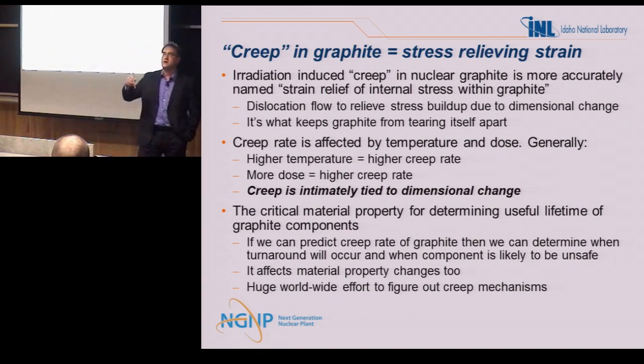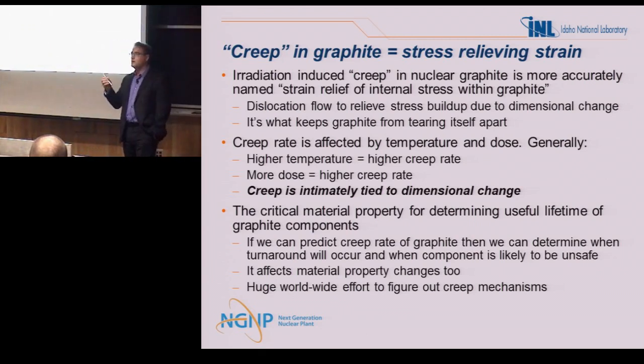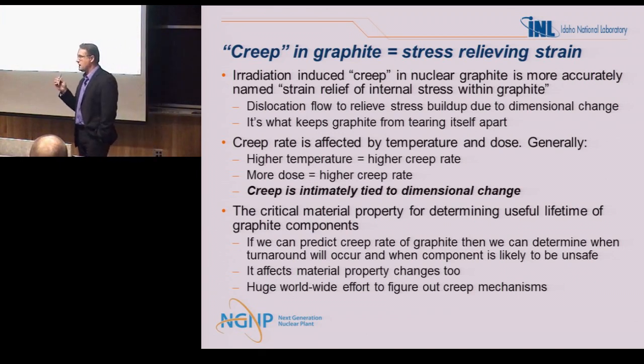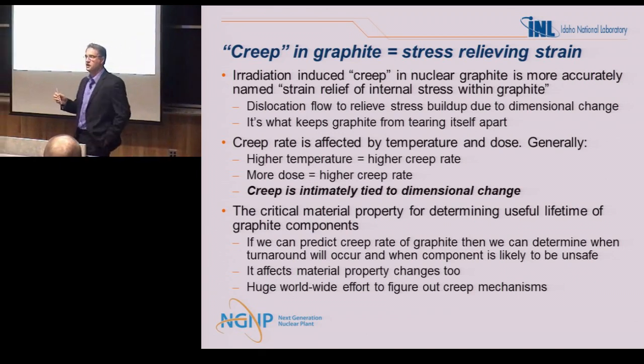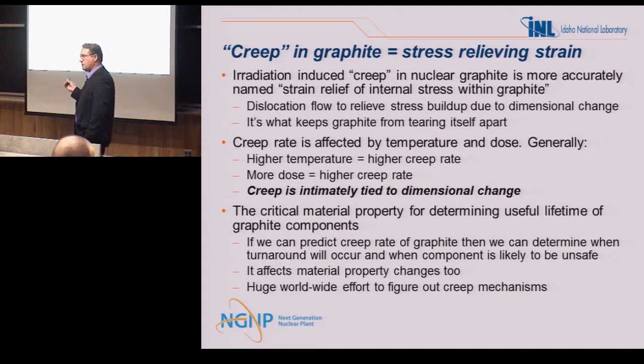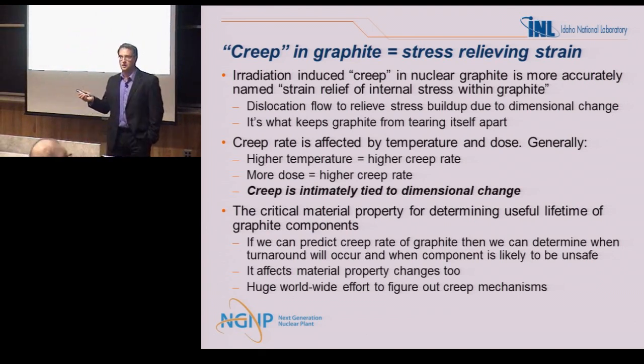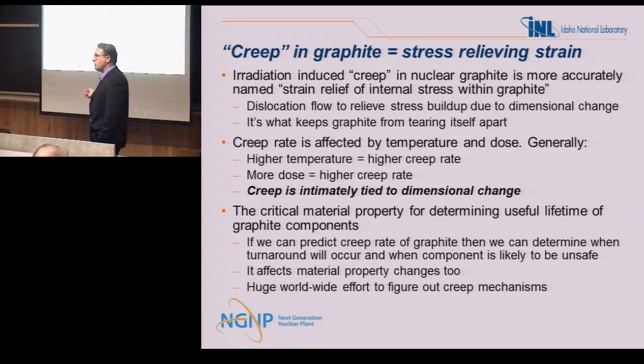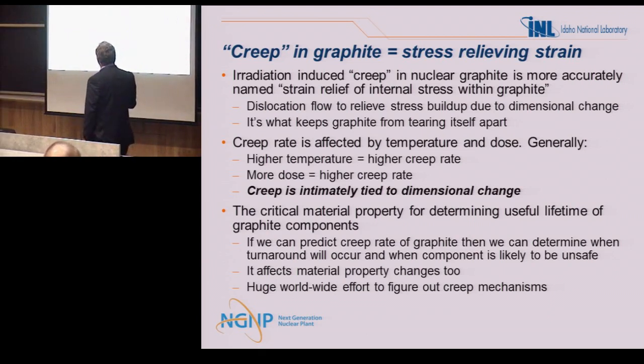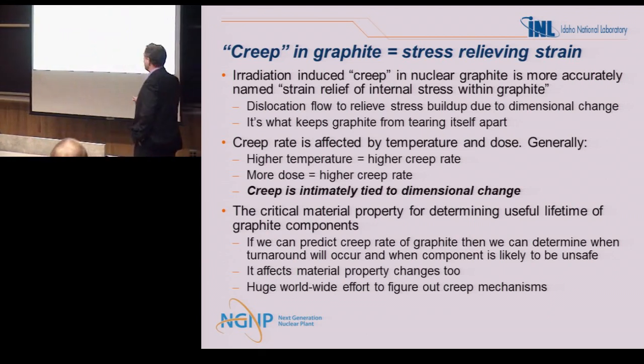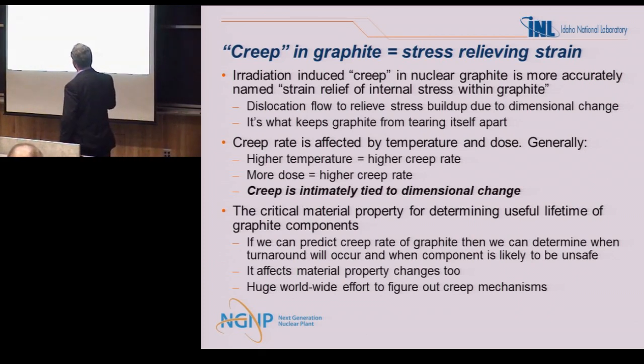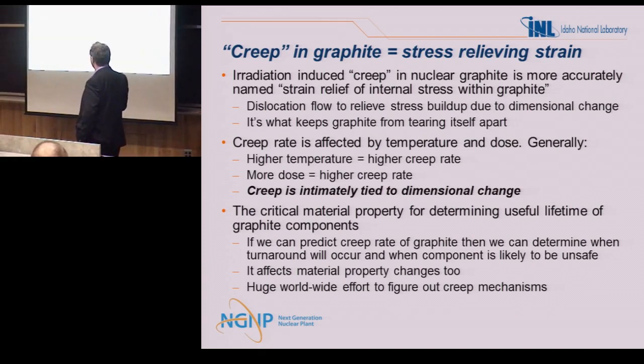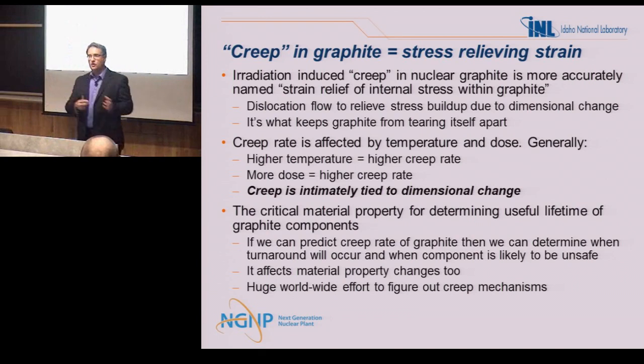The calculations are that if you had a graphite reactor, within about 3 or 4 months, it would literally have turned itself into large chunks. Another 3 or 4 months later, it would be about sand. All right, it literally tears itself apart without creep. Creep rate's affected by the temperature and the dose. Basically, the higher the temperature, the higher the creep, and the more dose, the higher the creep. Creep is intimately tied to dimensional change. Without dimensional change, there is no creep. Without creep, it literally tears itself apart.